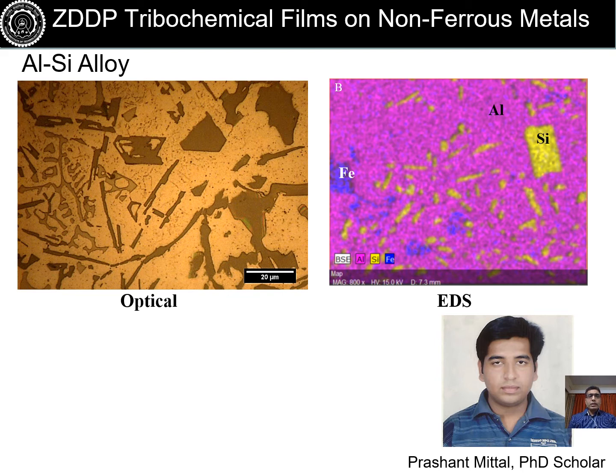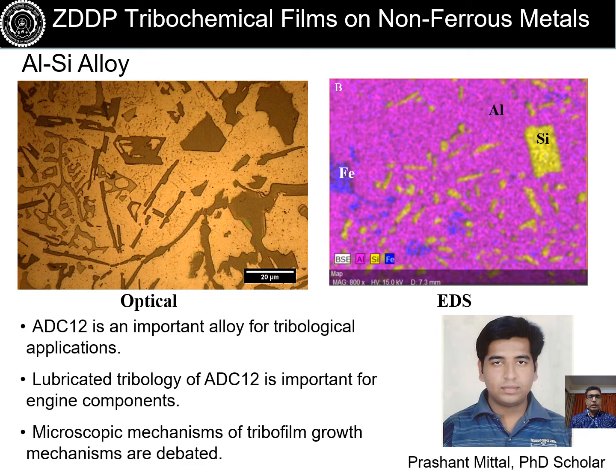So in terms of heterogeneity and looking at more realistic systems, we have started doing experiments now on different alloys. One such example is aluminum silicon alloys, which is heavily used in automotive engine block manufacturing. This alloy primarily has two phases, which is aluminum matrix, which is the light color region, and silicon phase. Of course, it has some intermetallics, iron-rich intermetallics as well, but those are not a significant fraction of the microstructure. Majority is silicon phase as well as the aluminum matrix, which is very soft aluminum region around hard silicon particles. So my student Prashant looked at interaction of ZDTP on these surfaces, and we looked at how these films develop on different regions of the surface, which has silicon and aluminum matrix.